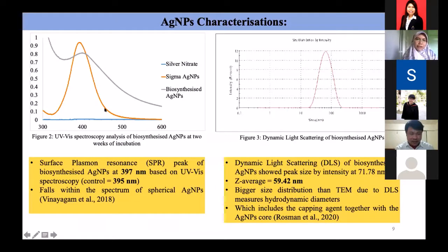Then we use this spectroscopy analysis. You can see the peak of our sample compared to the control. For the control we use silver nanoparticle from Sigma. Then we can detect the peak. Our peak is almost similar to the control peak, at 397 nanometer compared to control 395 nanometer. Within this peak, we can identify the silver nanoparticle in round shape.